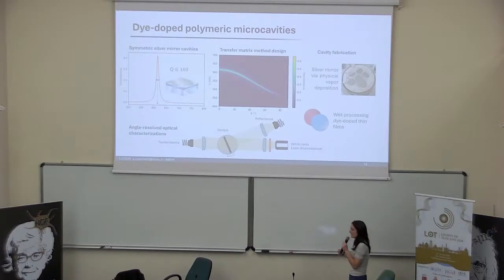In particular, this dye is a highly fluorescent small molecule laser dye. It is a very benchmark system, but it is a small molecule. So here the fabrication process was intentionally very simple. We want to study the trade-off between reaching a large strong coupling while maintaining good photoluminescence efficiency from our microcavity. So we start from a very basic design using the transfer matrix method in order to match the photonic mode with the material resonant transition. Now I will show you.